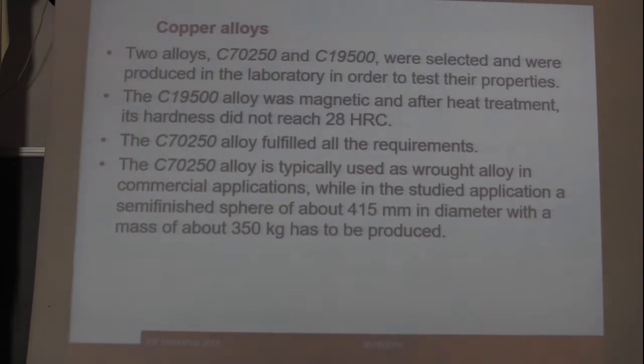Unfortunately, the C19-500 alloy was magnetic, and after heat treatment, its hardness did not reach the minimum value, which was 28 Rockwell C. The other alloy fulfilled all the requirements, but this alloy is commercially used as a brazing alloy and for producing very small items. So we need to keep in mind that we need to produce a sphere that has about 40 centimeters of diameter and a mass of about 350 kilograms. So we need to know the properties of the alloy in the as-cast conditions.